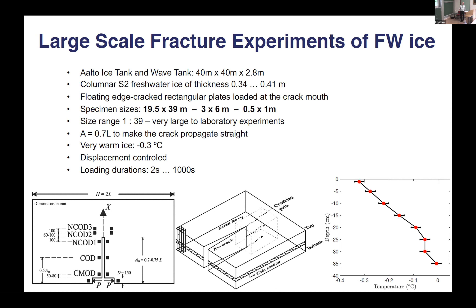We grew columnar ice to a thickness of 34 centimeters, and by the end of experiments it was 41 centimeters. The specimen sizes used were 19.5 by 39 meters, 3 by 6 meters, and 0.5 by 1 meter. Specimens were rectangular with a 1:2 ratio, with a crack of length 0.7 times the specimen length. When this long crack starts to grow in this geometry, it goes straight up, so we can measure what happens at the crack front.